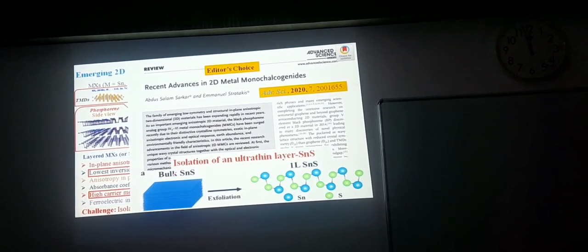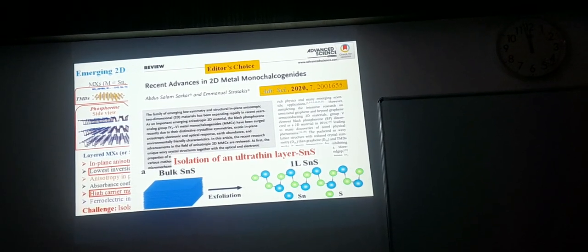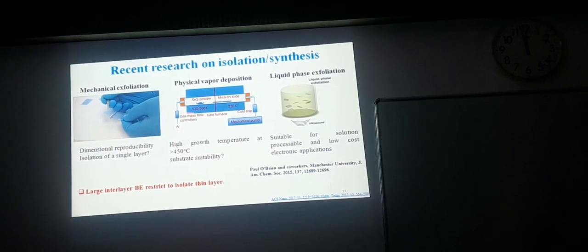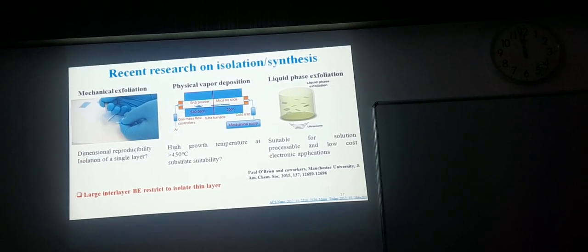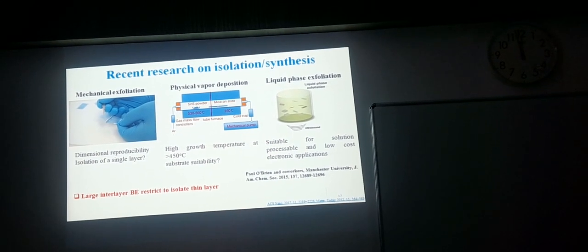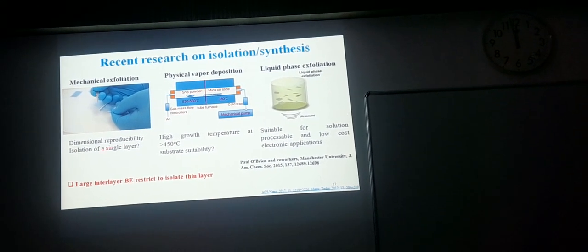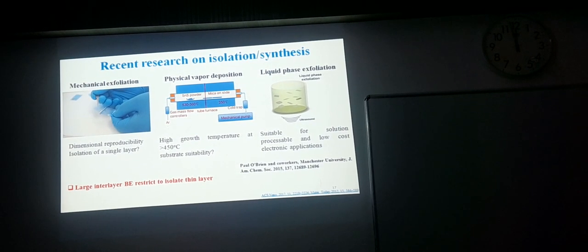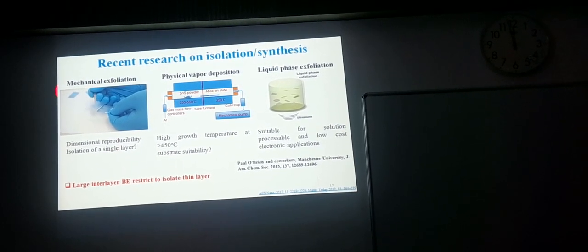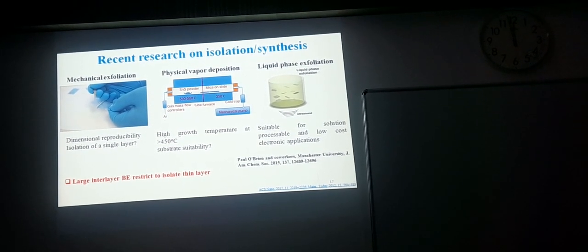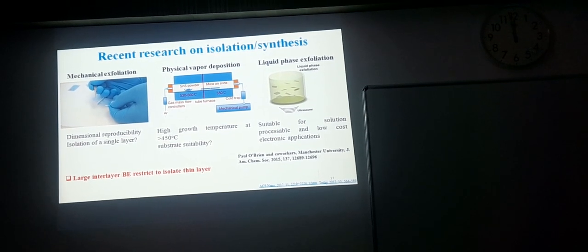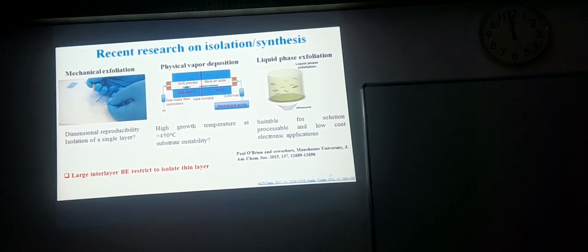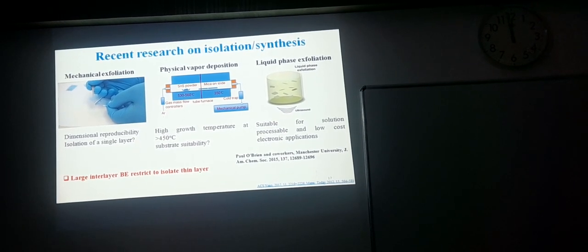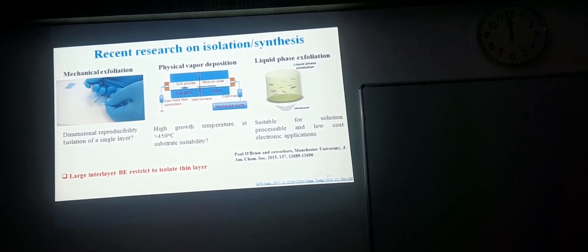Then our main focus was how we can create a single layer of this tin sulfide, which is a very important material. There are various methods or techniques that have been used in the past few years, not only for this material but for other two-dimensional materials. This is basically mechanical exfoliation, which many of us may know. This is the Scotch tape method, the technique used to produce graphene that won the Nobel Prize. It is a very simple method: if you have a 2D crystal, you peel it off multiple times and you can create a single layer that is a few nanometers thin, with a lateral dimension of a few hundred microns.